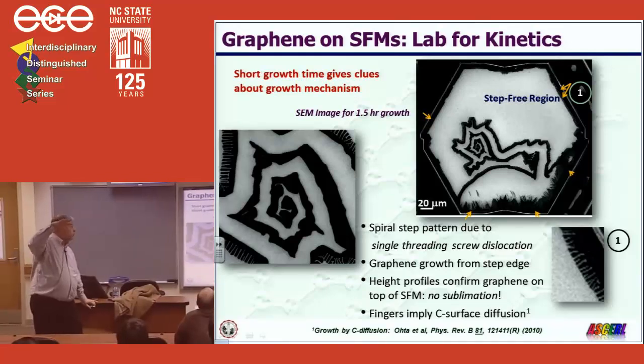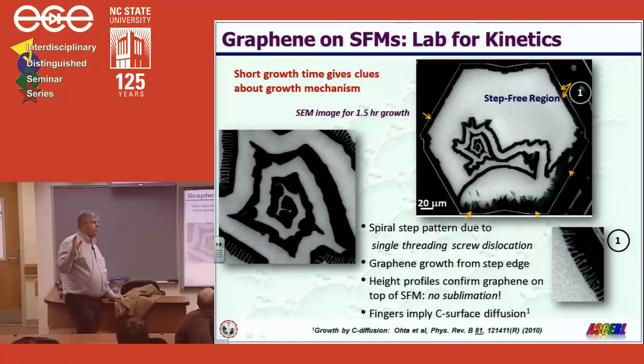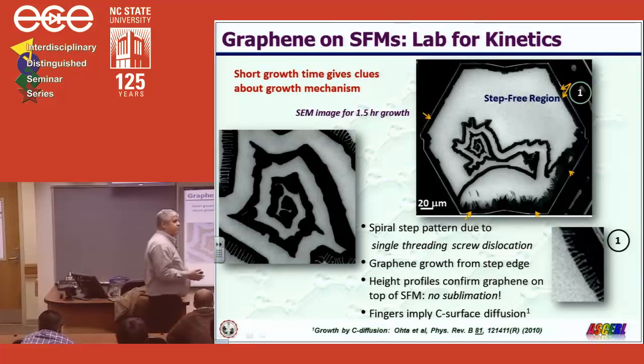And Taisuke Ota recently demonstrated that carbon diffusion process from a step edge that is not perfectly straight should lead to the finger formation of graphene. So this picture not only confirms the model of Taisuke, but also indicates that the growth mechanism on these mesas is by carbon diffusion, and it's carbon diffusion from a step edge.